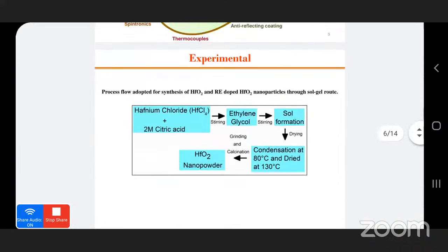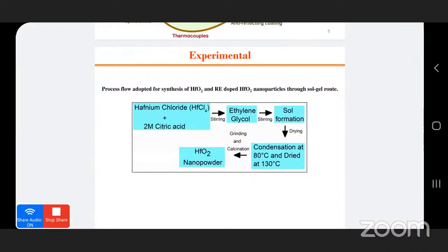So in this particular work, we have prepared these hafnia nanoparticles using a simple, facile sol-gel method. We took the hafnium chloride precursor and mixed it with citric acid. Then we followed a step-by-step procedure to finally get the hafnium nanopowder. We calcined it at different temperatures, and we found that when we calcine this hafnium oxide at 900 degrees Celsius, we get very good crystallinity.